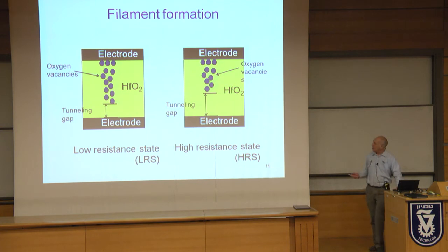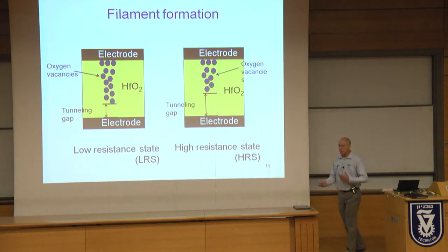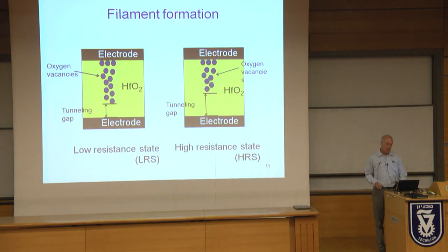And this is the way we think about the filaments. Here are the two electrodes, the hafnium dioxide, and some oxygen vacancy filaments. And the main question we have in mind is actually what is the size of this filament? We think it's very small. It can be just a few vacancies that can make a difference between the high resistance state and the low resistance state. So how many vacancies do we actually have to move in order to switch a device from on to off? That's, I think, an interesting question.